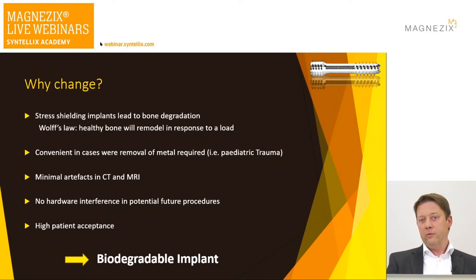You have to ask the question: if titanium and steel screws work well, why should you change? Because I normally spend a lot of time removing metal due to the potential for stress shielding. If you have a sturdy implant, you have bone degradation beside it — bone needs loads to keep its density. That's why I tend to take the metal out, and that was the first need for a bioabsorbable implant.